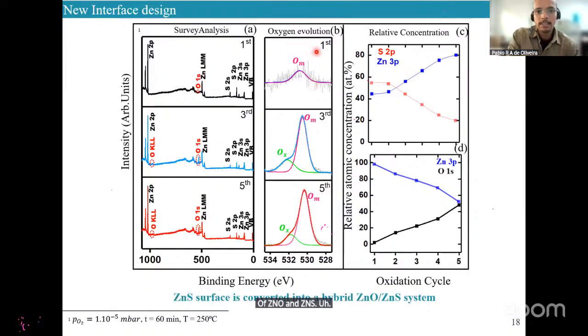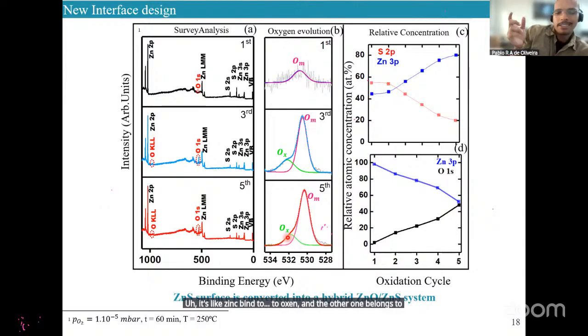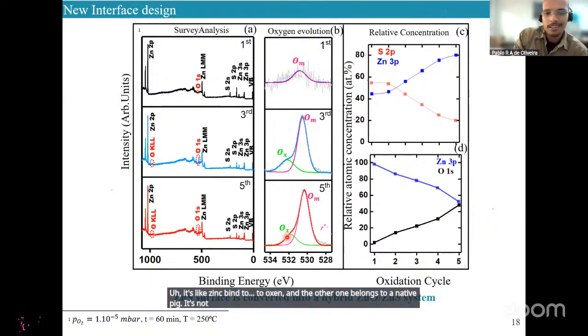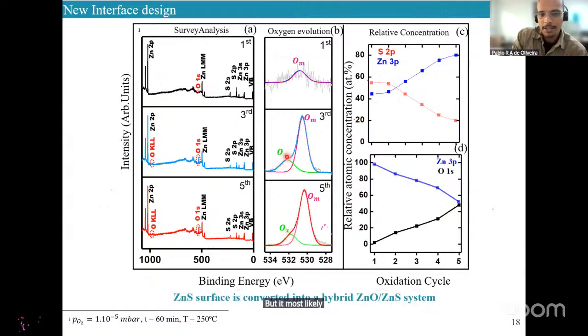By analyzing the oxygen evolution, we can resolve this peak into 2 components. Most likely the one at 530 eV is zinc bound to oxygen, and the other one belongs to a native peak. It's not defined in the literature, but it's most likely water in the chamber, or around the lattice, surrounding the oxygen sites. But what is most important here is the relative concentration of sulfur and zinc.